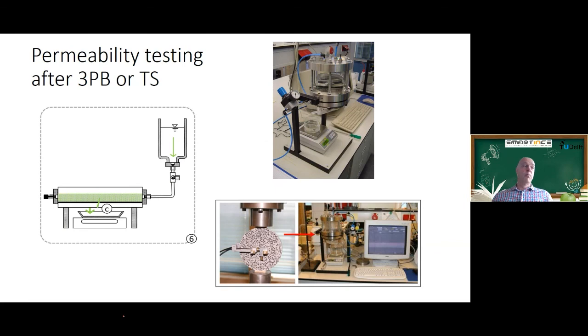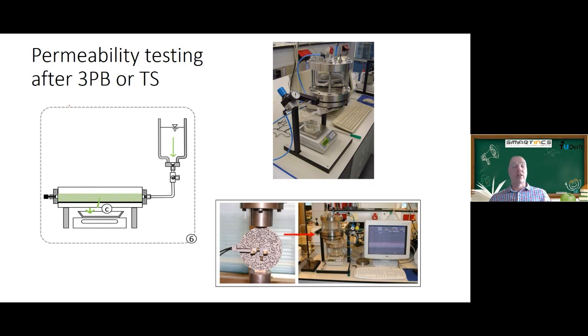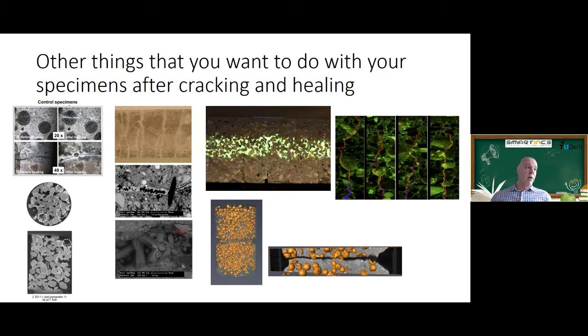After the test, you probably want to study permeability — either through the crack or by putting the sample in water and measuring how much water it takes up. You can also do impregnation, look under the microscope, or do CT scans. All of these things you can do afterwards with your cracked sample. You have to consider what you will do with it after cracking when you are designing your test, designing your specimen, and creating the fracture.